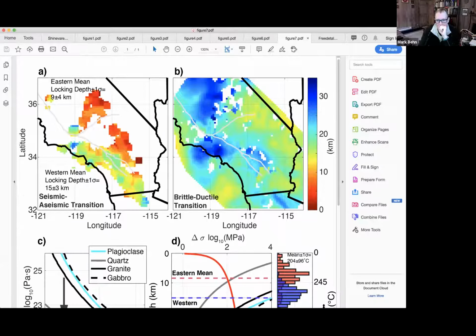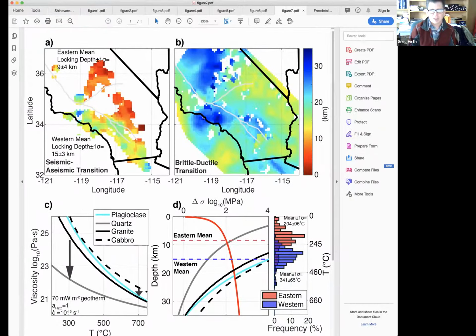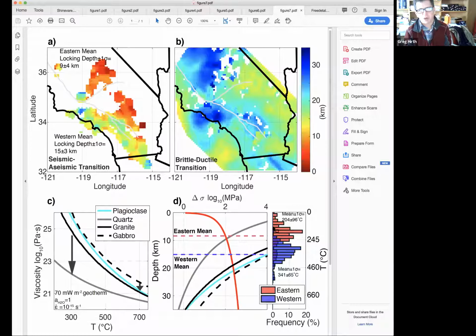Yeah, that's a really important point. The models that Mark was just showing were, if you go back to Billy's map of viscosity. Sure, just a second. It ties directly back into what Andy was just showing. This one? Yeah, because you see the higher viscosity and the deeper locking depth in the area around the Peninsular Ranges, a little south of there. Well, that's the Sierra Nevada, but also in there, yeah. And then in the Salton Trough, you get the shallower brittle ductile transition and then associated lower viscosity.